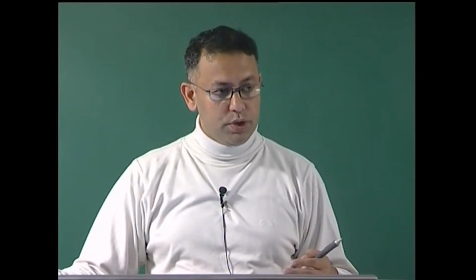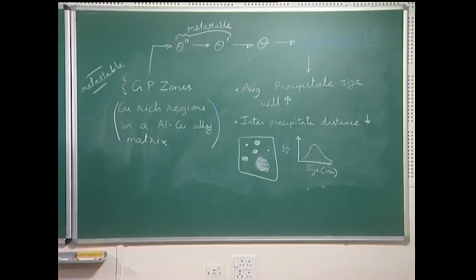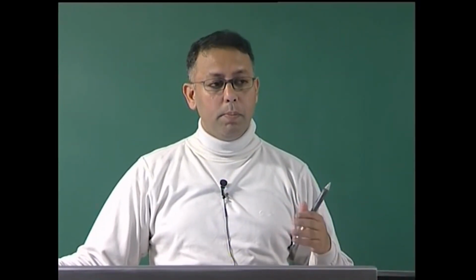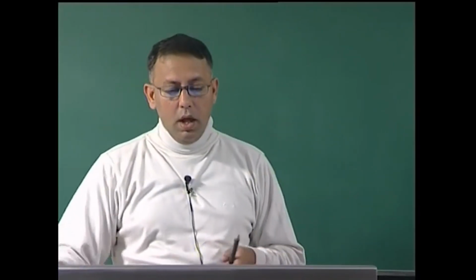Again, with the temporal evolution of the system, the shape of these particles may also change. For instance, in some systems, take the precipitation of gamma prime particles. This gamma prime initially precipitates spherically, but later on when the precipitate becomes semi coherent or incoherent, it assumes a certain shape which could be cuboidal or a cube. Therefore, a spherical precipitate with time changes into a cuboidal shape, and this is because of the temporal evolution of the precipitate, which is intimately related to the interface changing from coherent to incoherent. Therefore, when I am using the term distribution of phases, there are multiple parameters which I need to keep in view, and all this is towards understanding the properties of the material.